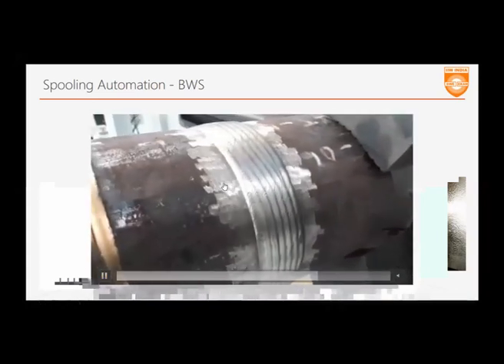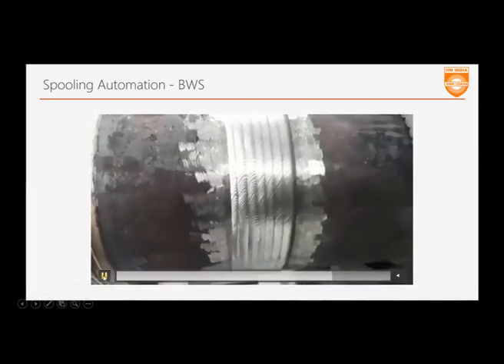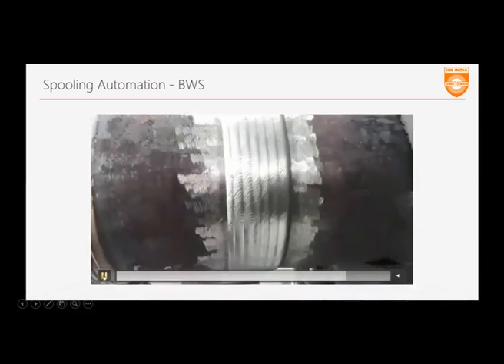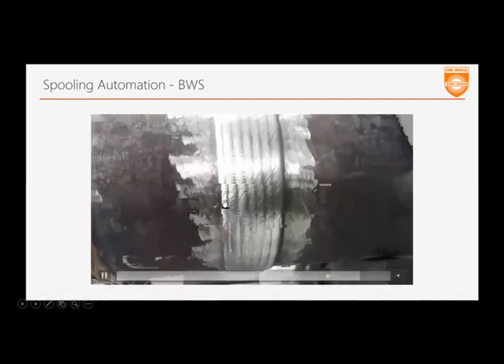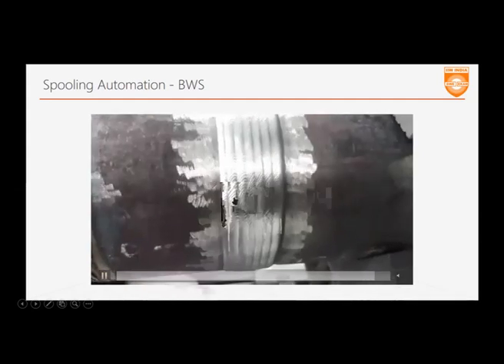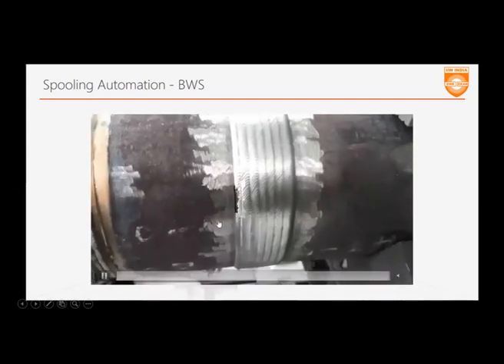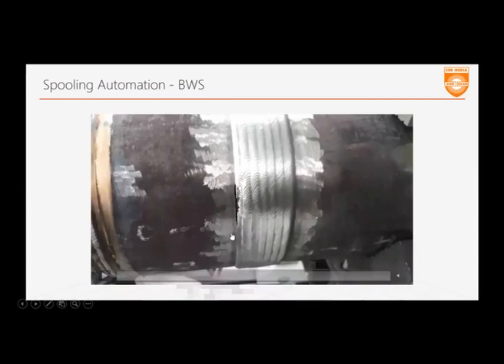It is pre-programmed, so once you put in the diameter of the pipe, it will maintain a linear speed. Once the 360 degrees is over, it would move on to the next one, weld the next run, and the next run. It will keep doing it on its own with minimum intervention by the operator. When you're doing multi-pass, when the second pass comes, because of the AVC, it will again maintain the same arc gap and maintain the voltage that you want.